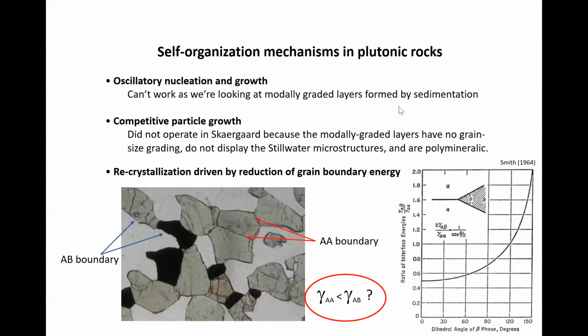There's a third patterning mechanism, and that's that we get reorganization, sort of modal reorganization that's driven by reductions of grain boundary energy. Now, this is sort of like texture equilibration, but it's based on the premise that grain boundaries between 2 grains of the same phase, AA grain boundaries, like these ones here, have got a lower energy than grain boundaries between 2 minerals of different phases, which is AB boundaries, so these ones here.